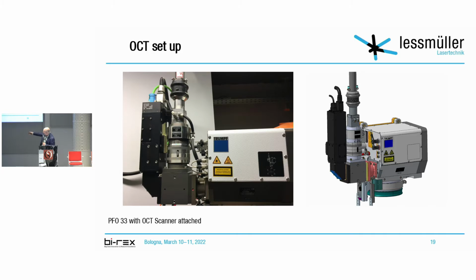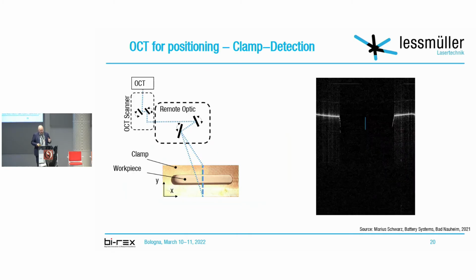OCT scanner. So this is all that you need for pre, in, and post measurement. In this application, which is battery welding for Mercedes, the first step that we do, we make one short scan across the clamping in order to identify the clamping edges, and then we reposition the beam exactly in the middle of the clamping in order not to weld the clamping onto the part, but to be in the middle.